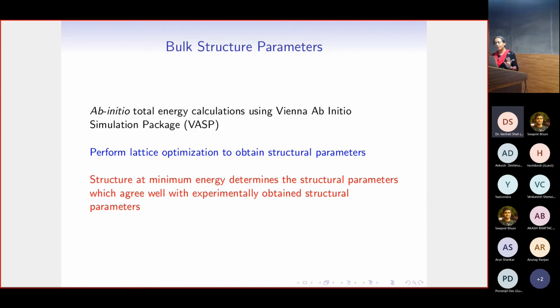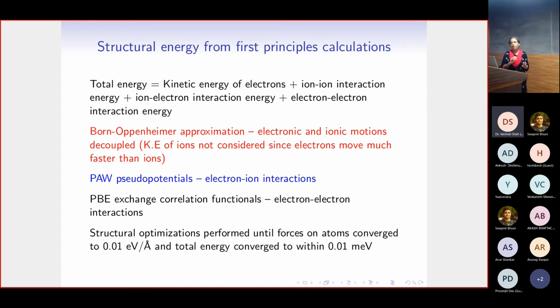Okay, and typically this has been from first principles. It is known that whatever lattice parameters you obtain give a very good agreement with the experimentally obtained structure parameters. Although this is what is considered a 0 Kelvin theory, meaning there is no temperature in the calculations and the experiments are performed at a certain temperature, the agreement between the prediction from the theory and the experiments is very good.